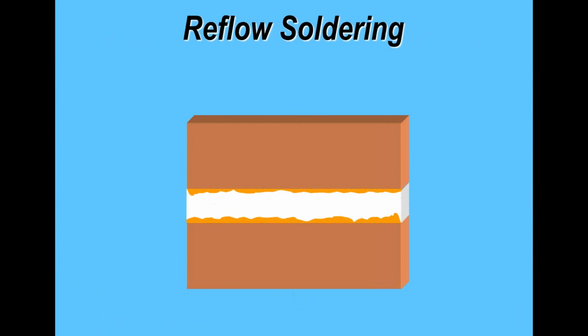So let's talk about the solder formation process, just so we're all looking at the same issues. Now, when we're soldering and making an interconnection, we're forming an intermetallic between the two surfaces that we're soldering to. The only exception to that is when you're soldering to a tin lead or lead-free solder-coated PCB, i.e. a solder level or a HASL board, where the intermetallic has already formed between the base material and the solder. If you're soldering to other surfaces, you're forming an intermetallic with the PCB at that time. That is the same as if you're soldering to the component termination if it's a solder coating, a liquid coating.